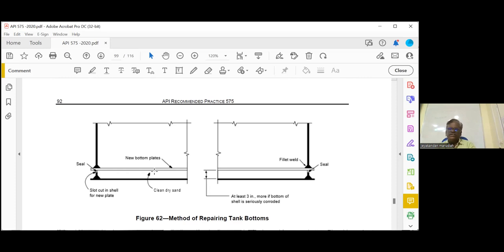Yes, sir. My question is, if you want to keep the cathodic protection for the new bottom, we need to remove the old bottom, right? Otherwise, no, if you are using a sand pad in between, old bottom removal is mandatory. Because, see, you can see the cursor here, if you put the anode here, instead of protecting the new bottom, sometimes the current can go to the old bottom. That possibility may be there. So you have to remove the old bottom. But if you are using a concrete pad, generally complete removal of the old bottom is not necessary because concrete is not a conductive material.